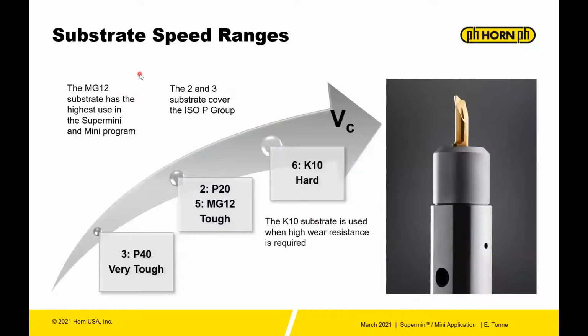If you look at, I think Horn grades are very straightforward. MG12 substrate is used heavily throughout the Supermini and the Mini programs. So the MG12 carbide. The 2 and the 3 substrate cover the ISO P group, and P40, the 3 substrate, is very tough. So if you have an unstable condition and lower cutting speeds, you could make use of the P40. But by and large, what you're going to see is what we call a 5 substrate, which is MG12. K10 is used if you have an abrasive material and you need higher hardness. So maybe you're running a little bit higher cutting speed.